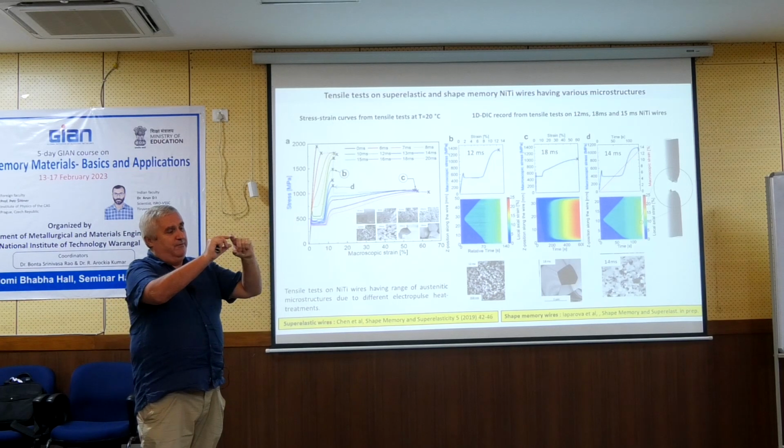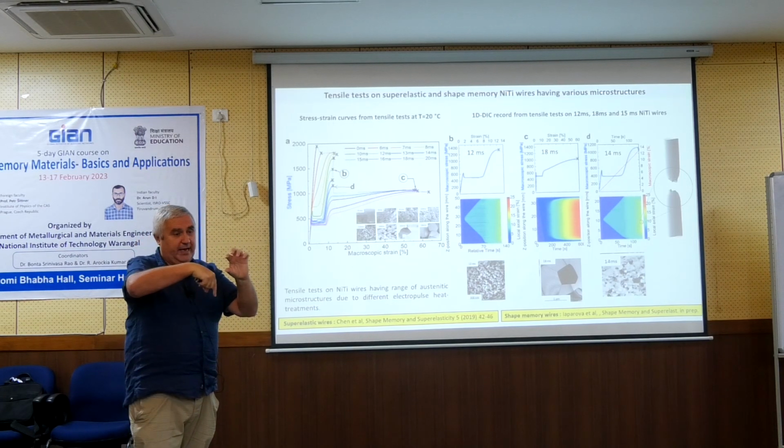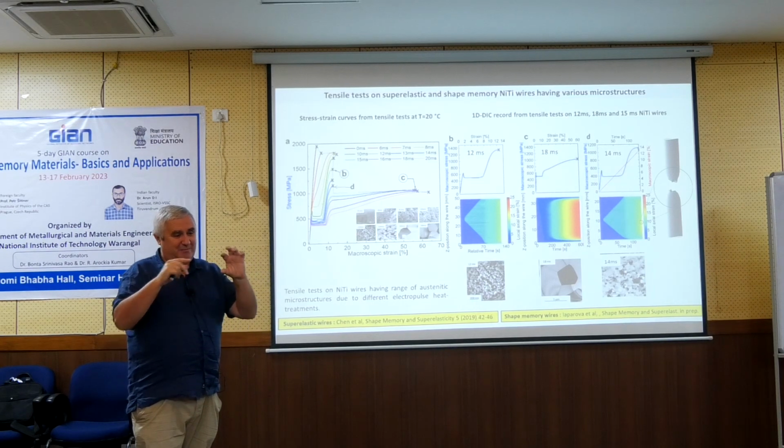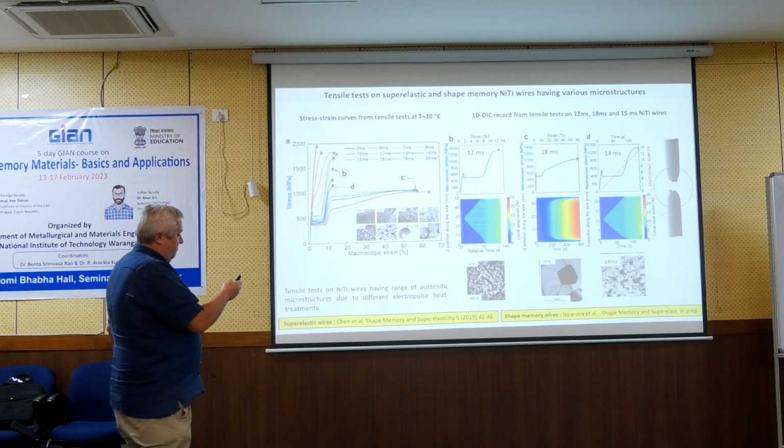So if my grain is 30 nanometers, I will have 2 grains on top of each other, and when looking through 2 grains in the TEM, I get a mishmash. So I must have 1 grain going through. So the grain must be much bigger than the thickness of the foil. And this is fulfilled for this 15 milliseconds.